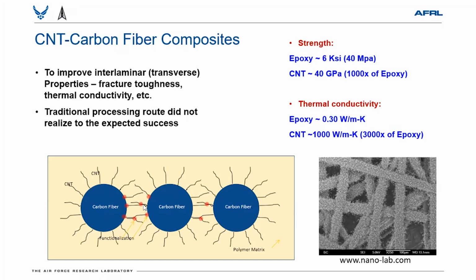But in reality, the achievement has not happened to the level of the expectation. Case in point, for example, epoxy strength is 6 KSI, whereas carbon nanotube is 40 GPa, versus 40 MPa. So carbon nanotube is 1,000 times stronger. So if you mix in, say, 1%, you expect the strength to go up proportionally, but that doesn't happen because of all the interface issues, how they are connected to each other.